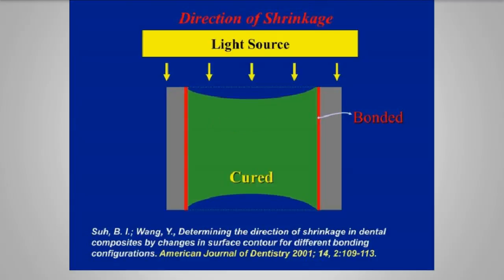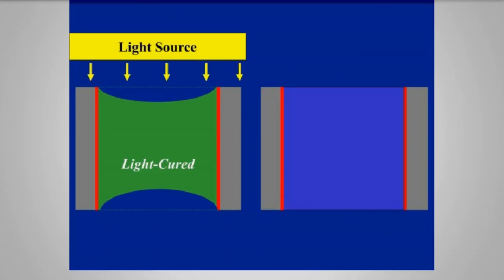You have uncured material. You light cure your material, you're still going to get the shrinkage at the top where the flow and the stress comes out, the isthmus of the class 1. But if you have poor adhesion techniques on your gingival seat, you can get up to 102 microns of liftoff. And here comes the hydraulics of flow. Here comes Brännström's theory. Here comes your tooth sensitivity issues. Unless you reduce the stress by using a glass ionomer or even a flowable liner, a Fuji liner, something like that to keep the stresses down.